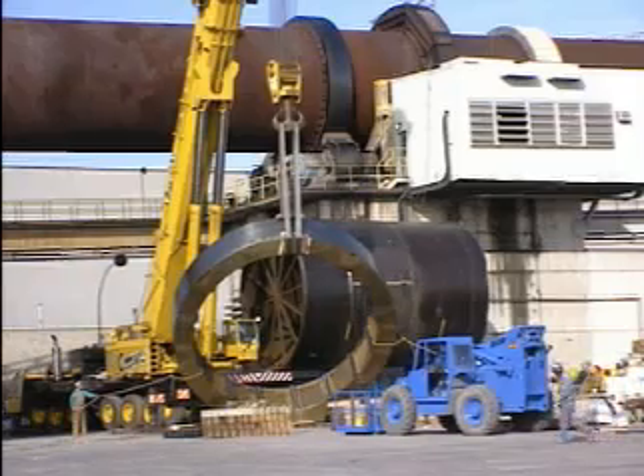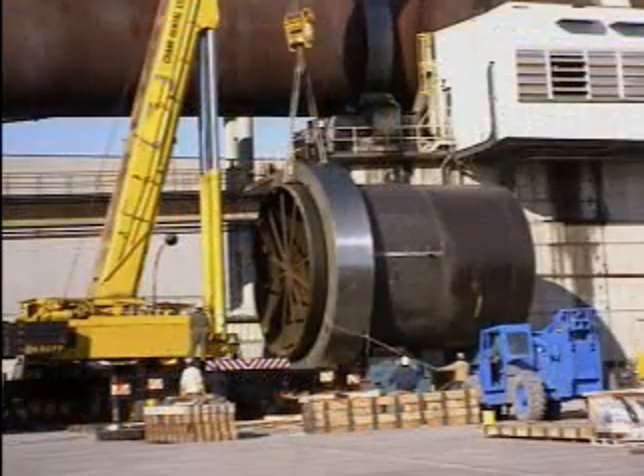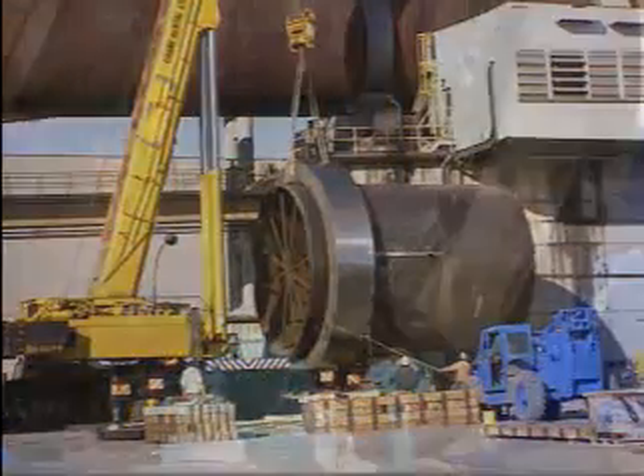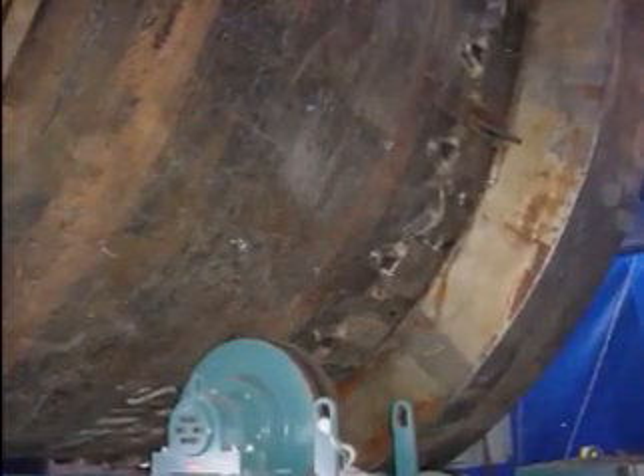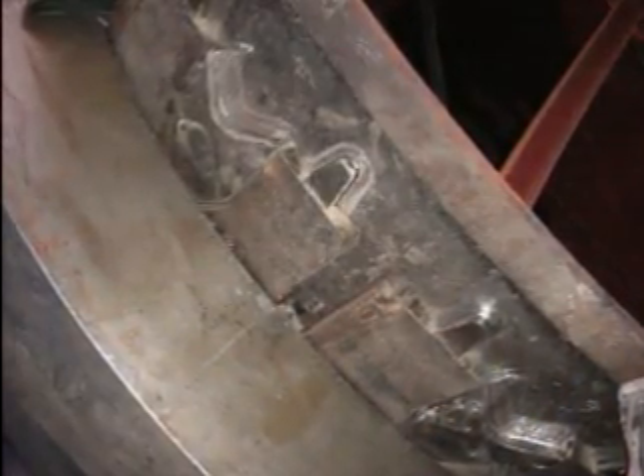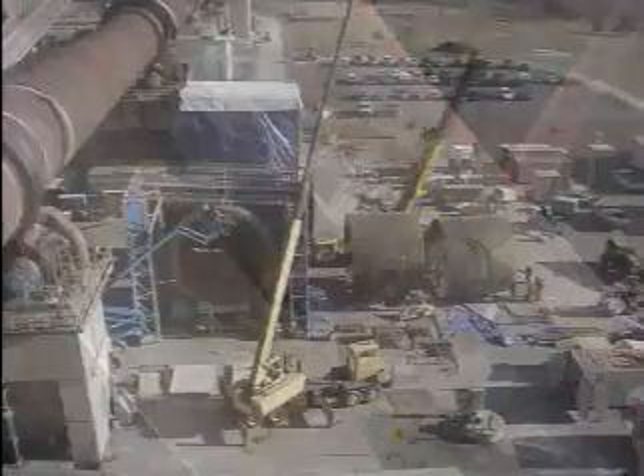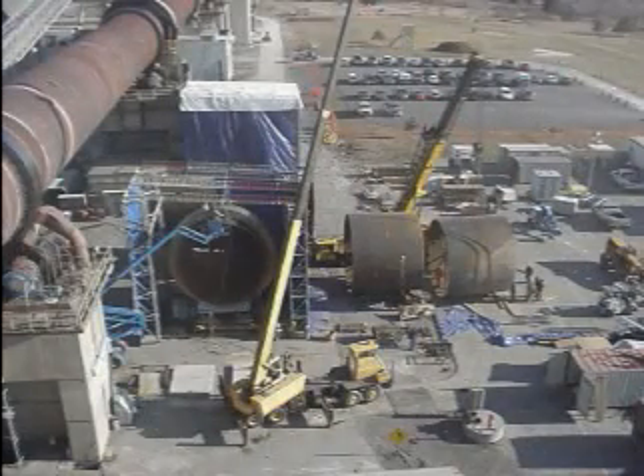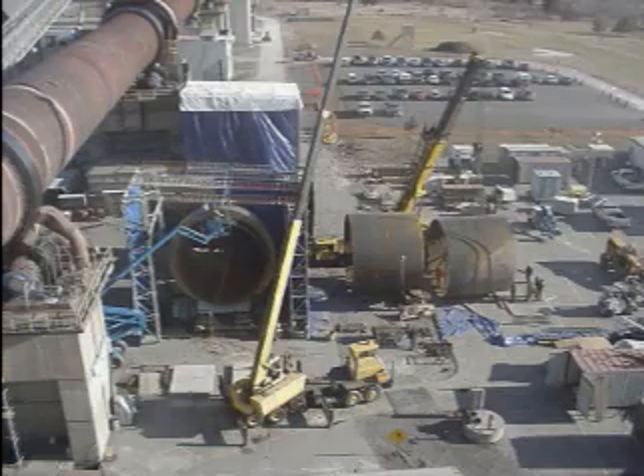Cranes were used to slide the enormous splined tires, weighing 100 and 157 tons each, onto two of the heavier kiln shell sections. The whole process resulted in the assembly taking place on pre-positioned power turn rolls, followed by the alignment and weld-out of the tire pad hardware, requiring 2 tons of electrode applied by the shielded metal arc welding process. A large weather shelter was erected around the assembly to help contain preheat temperatures and to protect it from the elements throughout the welding process.